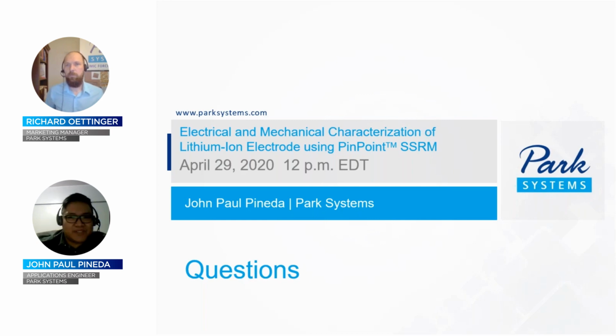Okay, so first of all, thank you everyone for listening to my presentation. If you are referring to the scanning speed, it depends mainly on your settings. For example, if you set a high pixel size and low scan rate, the scanning will take longer. For the Pinpoint SSRM example I have shown you, with a pixel size of about 250 by 150 pixels and a scan rate of about 0.22 hertz, it only took us less than 20 minutes to acquire the images.